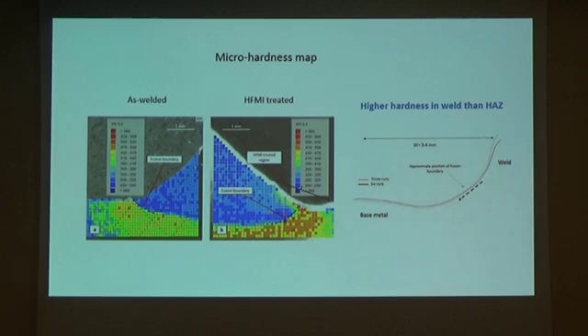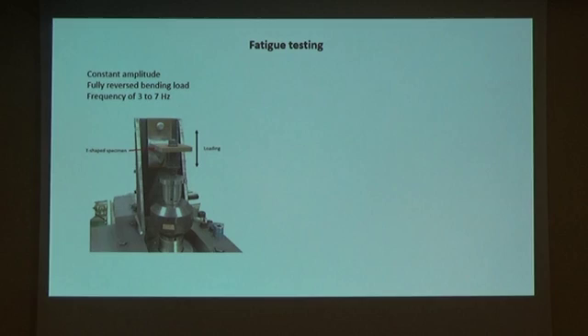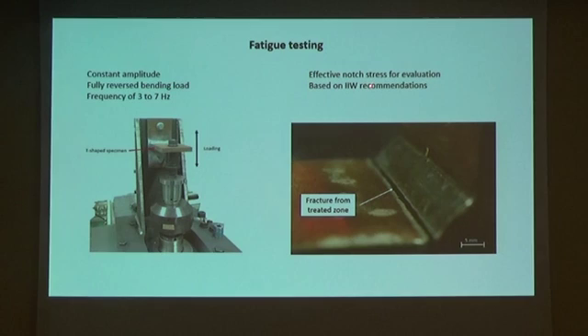Fatigue testing was done under constant amplitude, fully reversed bending load with a frequency of three to seven hertz. Here you see the fatigue loading setup for the T-joint sample. Evaluation was done using the effective notch stress method based on IIW (International Institute of Welding) recommendations.